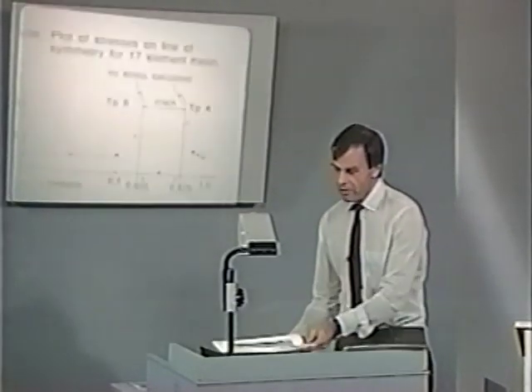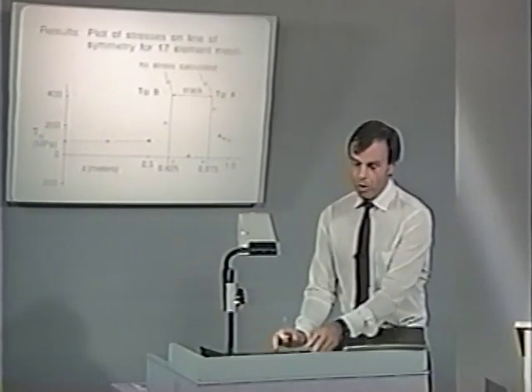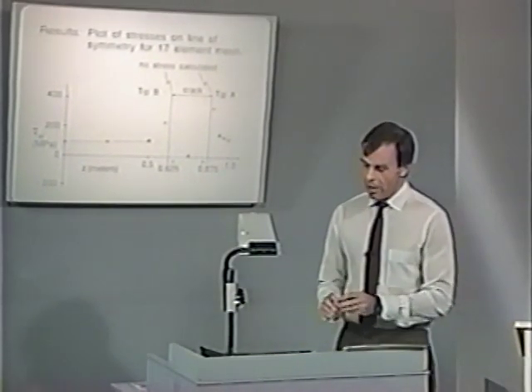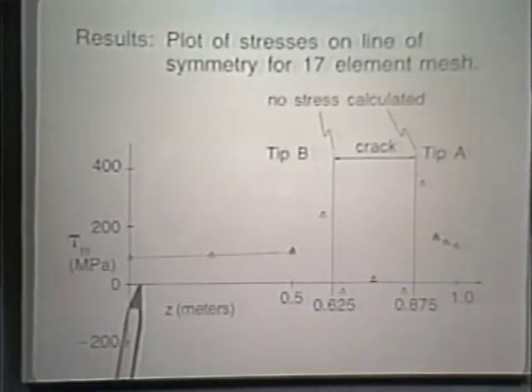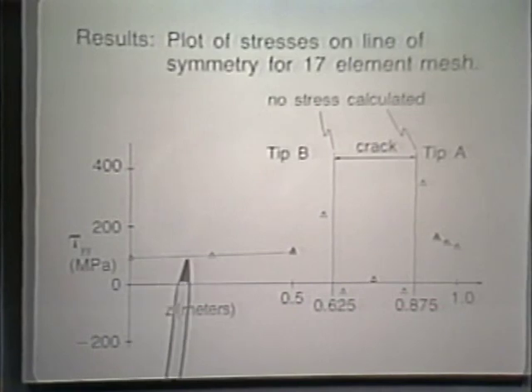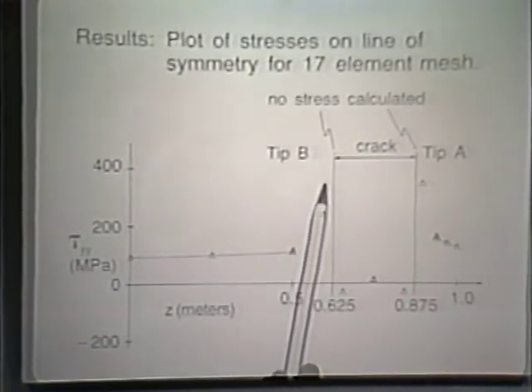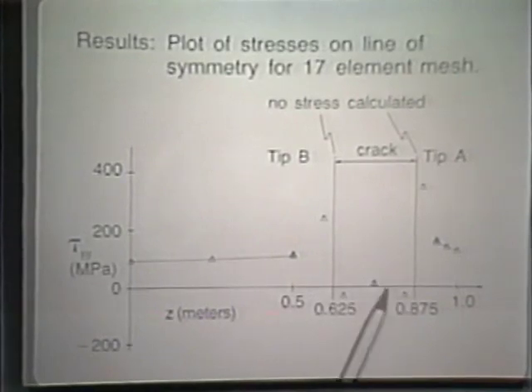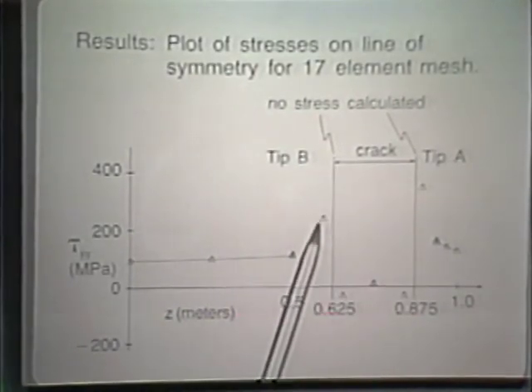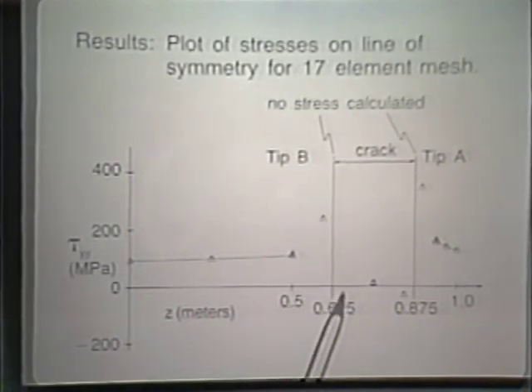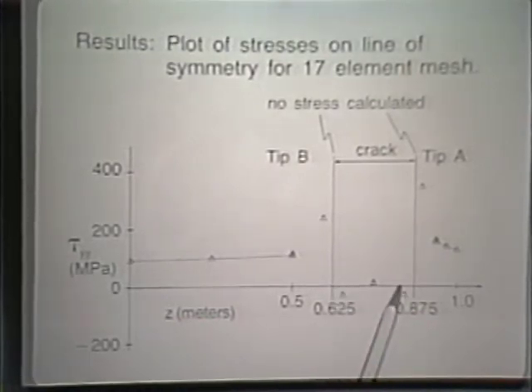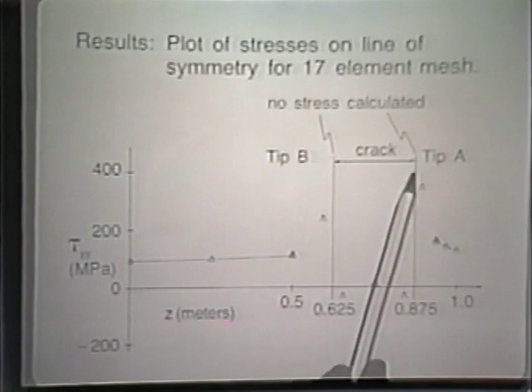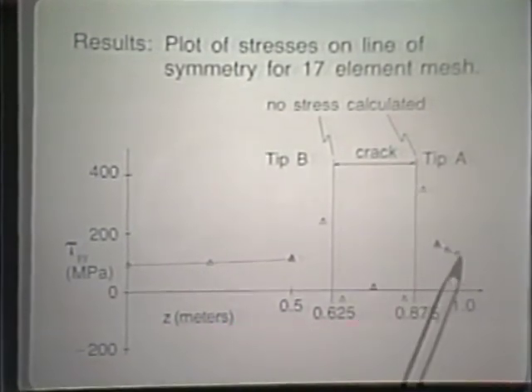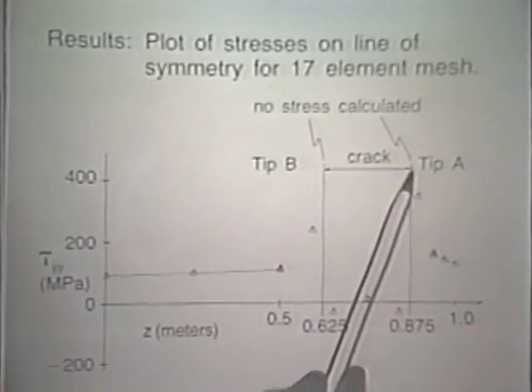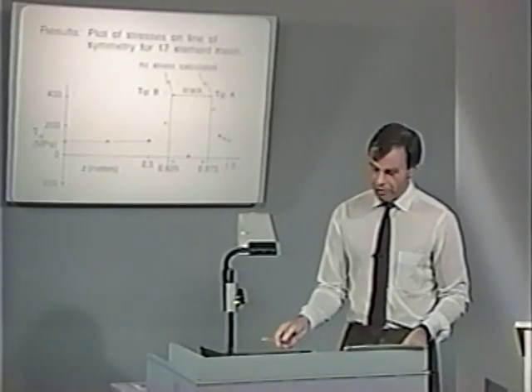If we look at the stress results, where we plot the stresses on the line of symmetry, we find that tau yy varies as shown here, then, of course, increases very rapidly near the crack. This is where the crack is. It increases very rapidly, then drops down to very close to zero. Of course, it should be zero right in here. And here we have, coming from the other side to crack tip A, this very rapid variation in stresses. These are the stresses tau yy.